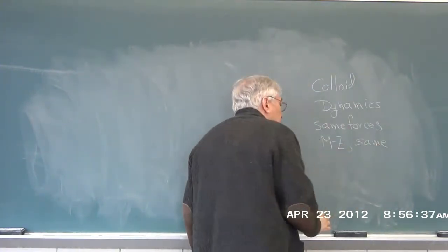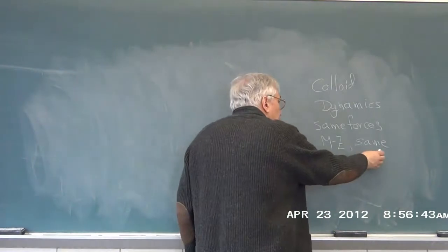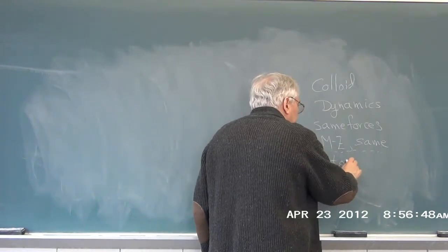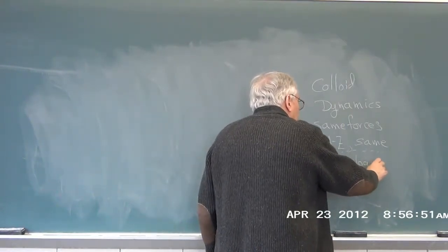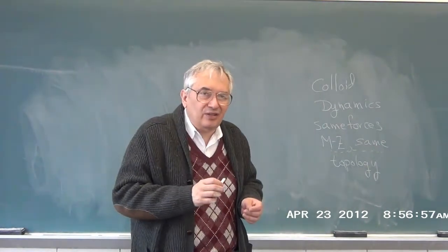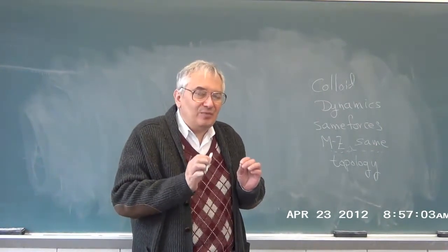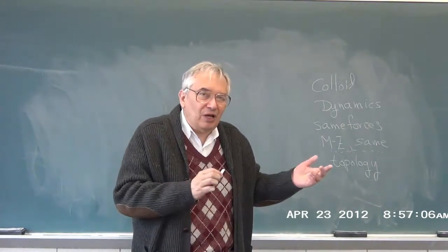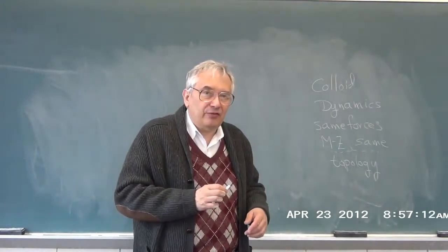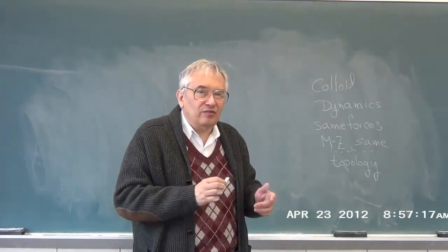That is, you are looking at heavily damped motions of many interacting objects. The difference between colloids and polymers is topology. That is, spherical colloids cannot tie each other in knots. Polymers can certainly do so. Whether this is dynamically important is a separate question, but certainly the two topologies are not the same. Colloids can jam, that is, if you have something that's like 60% by volume spheres, it doesn't flow very smoothly.